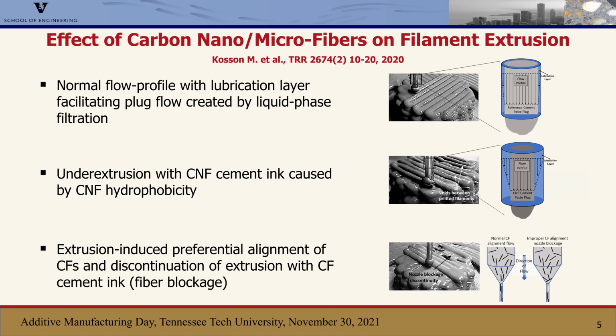But one very important thing that needs to be considered, and what we found when we printed with carbon nanofibers, is that if you use an internal reinforcement or an internal material that is hydrophobic, it can add to that driving force with the extrusion pressure so that you get more water coming out of your printed filament, and you can have a thicker lubrication layer, which can lead to under extrusion, as you can see here in the middle picture on the right, where the filaments are printed much thinner and you get significant gaps between your filaments.